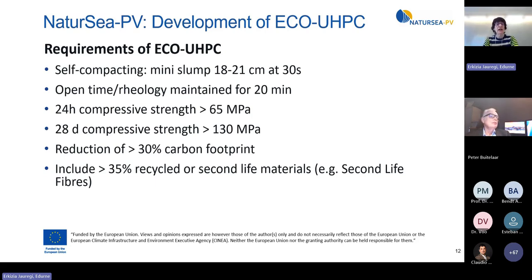in the project. First, we set up the requirements for this eco-ultra high performance concrete. It has to be self-compacting, with open time maintained for 20 minutes. The 24-hour compressive strength should be higher than 65 megapascals. At 28 days, compressive strength should be higher than 130 megapascals. We want to reduce the carbon footprint more than 30% and include more than 35% recycled or second life materials, for example, second life fibers.